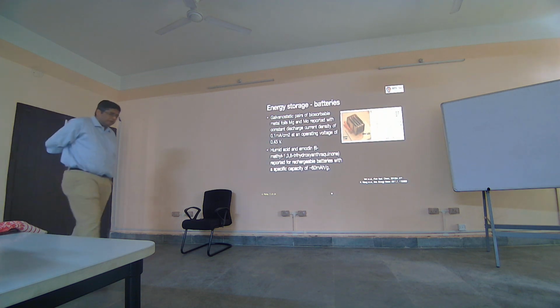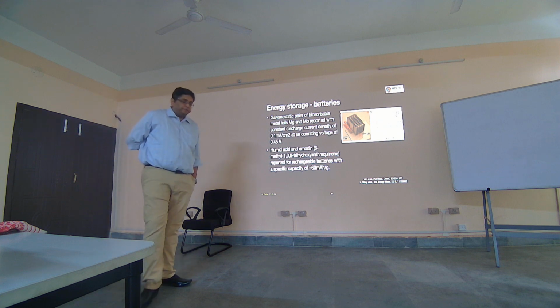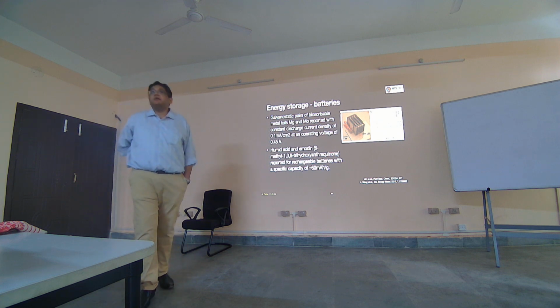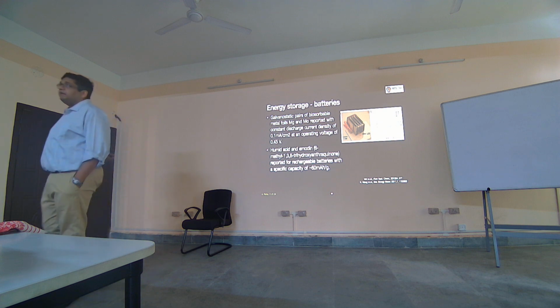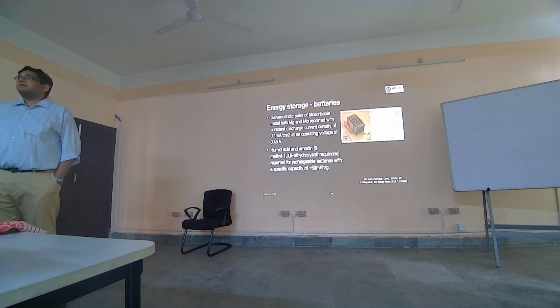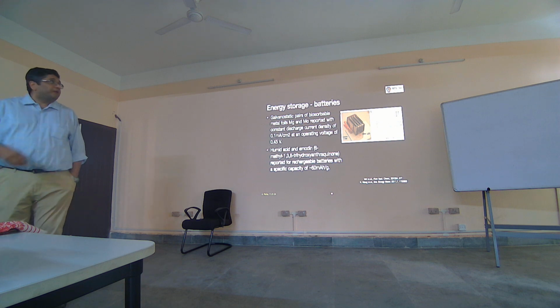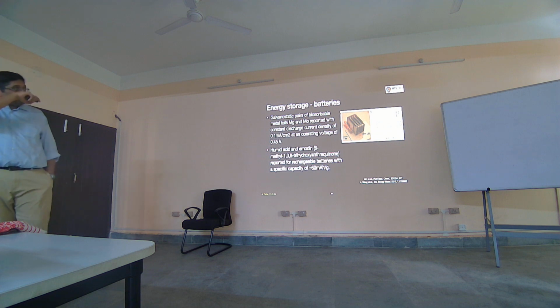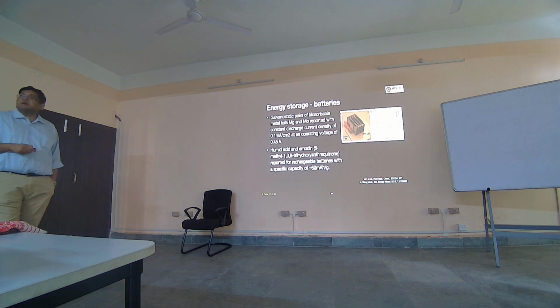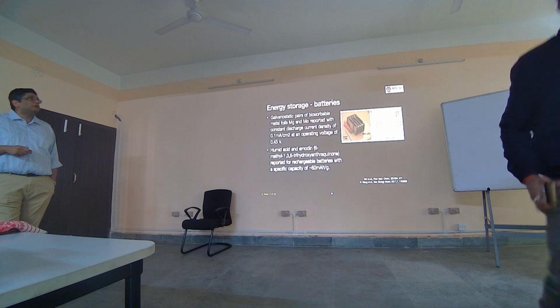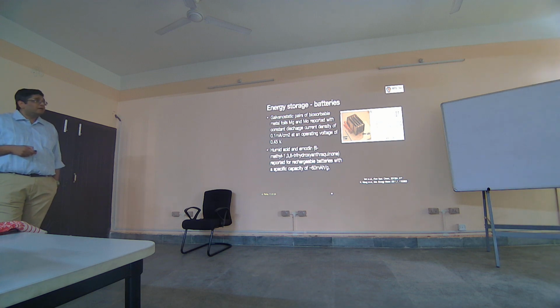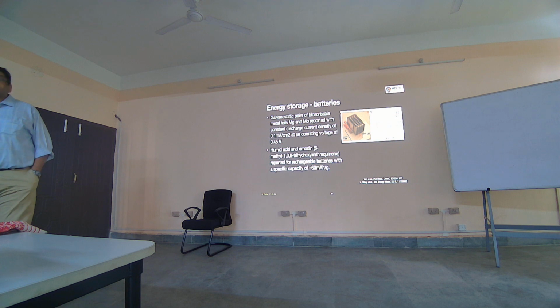An important component of these implantable electronics is energy sources, right? Because anytime, even a pacemaker, right? Pacemaker has a battery under it. So the question is, are there better ways to make batteries? So people have been working on this. Bioresorbable films like magnesium and molybdenum have been used to generate a battery. It has pretty low power density. So again, given that the application is for a week or a couple of weeks, which has to resolve again, the application, it's pretty good numbers.